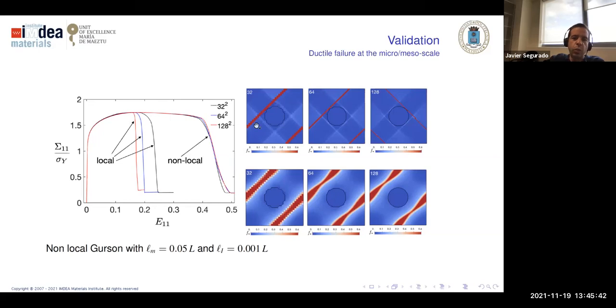Okay, you see that when we make the mesh smaller and smaller, the result changes and the energy dissipated changes. That is not good. On the contrary, whenever we introduce this gradient regularization within FFT, we see that the size of the band is totally given by the characteristic length. So if we refine, the only thing that we get is a more accurate result, but macroscopically, the result is equivalent, okay? So energy is preserved, and this is what we wanted.